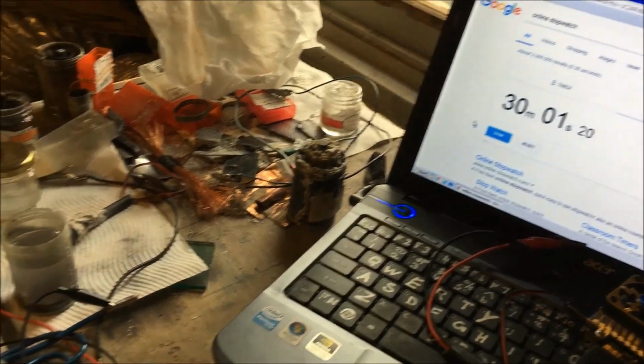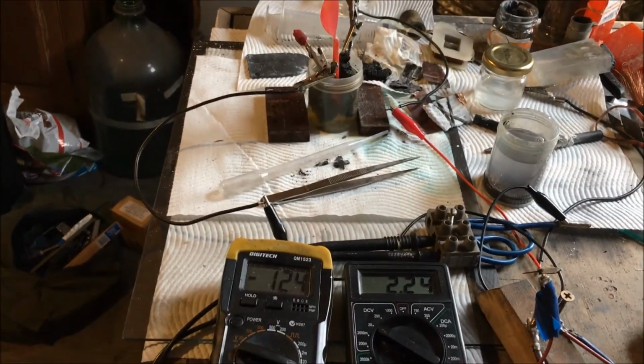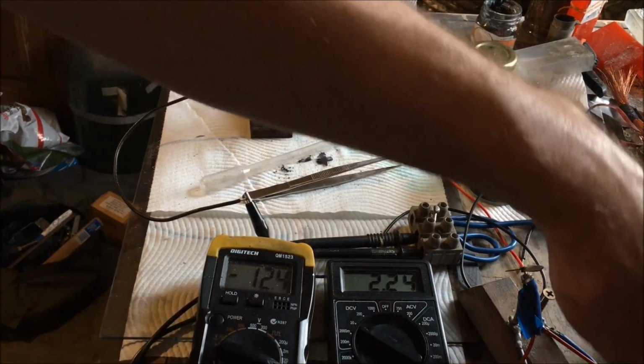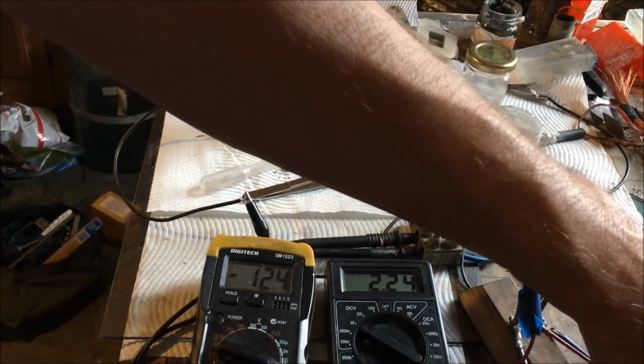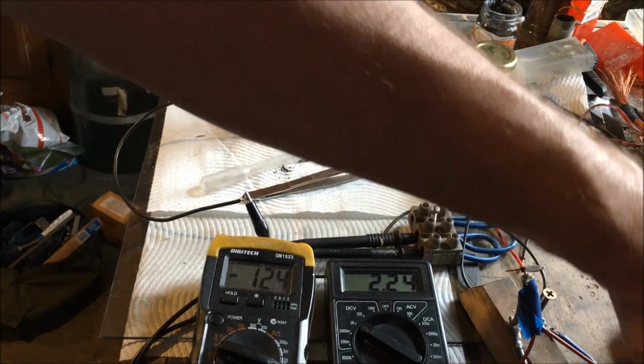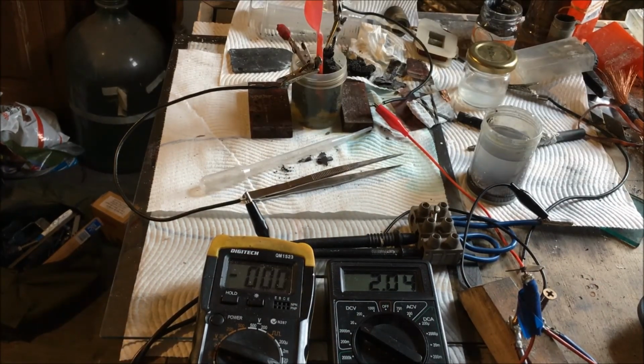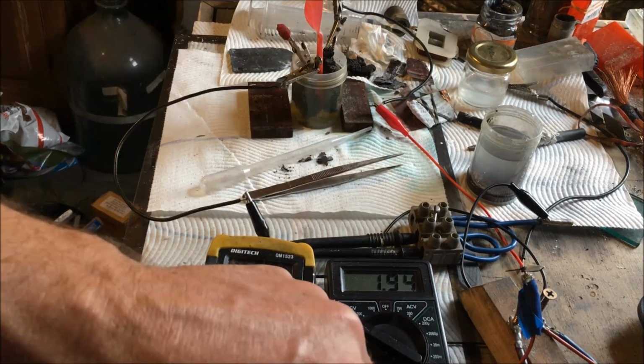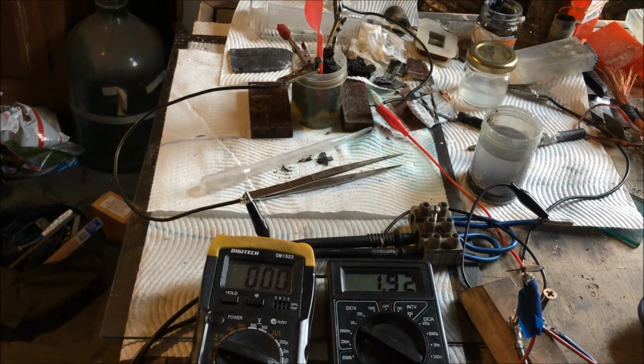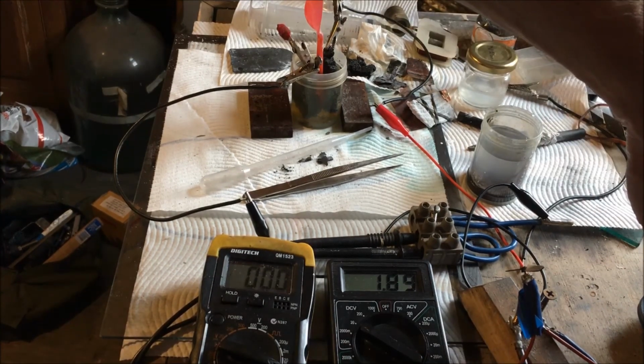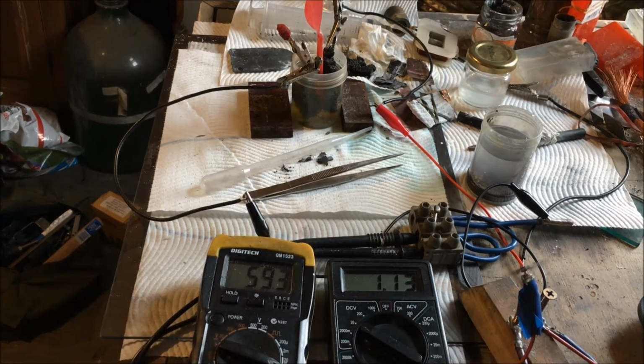Okay, it's only been half hour. I don't think an hour's very good on this cell, going by what the last results anyway, so we'll do half hour. Let's reset this timer. So this test has the larger carbon cell as the positive, disconnecting, dropping down around about the same speed as it normally does. It will go to 1, I reckon, eventually. So we'll test the load out. See if we get anything extra. We haven't got past the 10-minute barrier yet. Same milliamps as the small cell, 60.